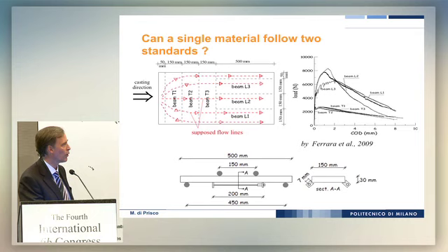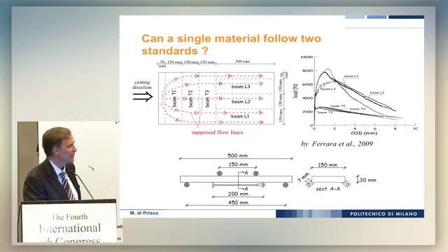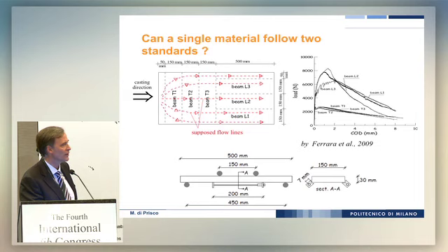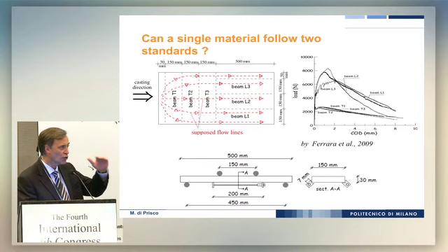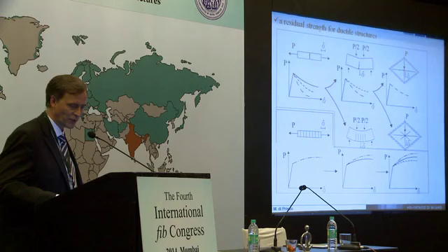And in some cases, especially when you have a thin-walled element, the best test is something which is not notched, because in this way you can really appreciate also eventually the sedimentation of the fiber inside the thickness, and so you can have really an idea if your material with a certain thickness is hardening or not in bending. That sometimes makes a difference.